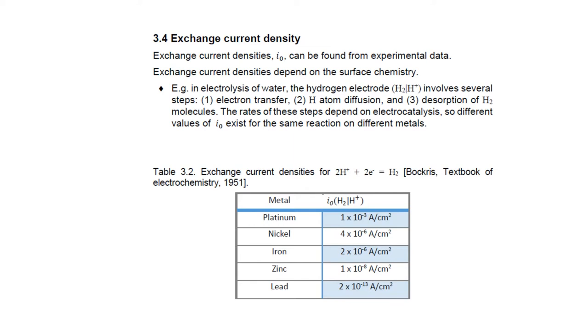Section 3.4 tells us the exchange current density of some process, this important i-naught value, can be found from experimental data. We will soon have an equation which describes the net current density affecting a metal surface as a function of the applied polarization. So if we measure the net current density for various applied polarizations, we can fit the parameters of that equation, and in that way we can infer one of the parameters, the exchange current density of whatever electrode process is happening.